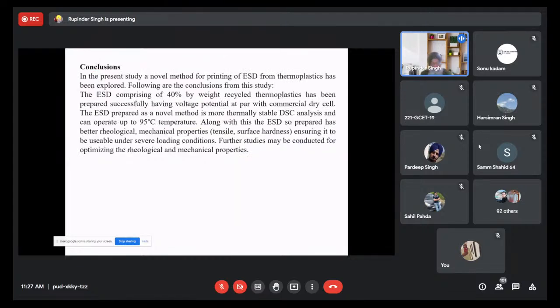We did the thermal analysis like I explained in the previous case, and what we observed in the repeated heating-cooling cycle, from room temperature to 300, then coming back to room temperature, is that my cell was stable up to 95 degrees. Whereas our commercial cells give us the desired output only up to a temperature of 55. Right, so we were able to use 40% of the plastic solid waste, and then I can use it at very high temperature. The third important thing is, with 3D printing, I am getting design flexibility.